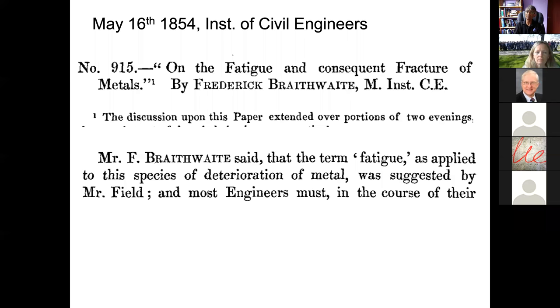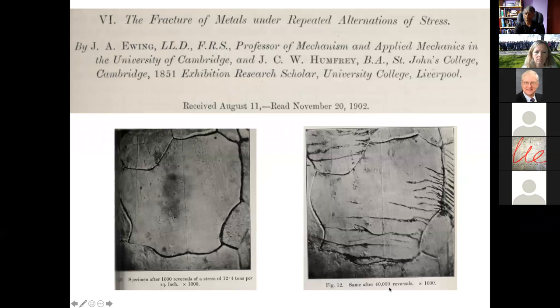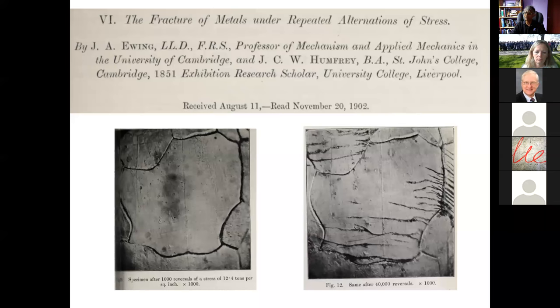The original paper was in 1854, and in 1902 these might be the first metallographic observations to show that even though you are repeatedly loading the material at a stress well below the macroscopic yield stress, there are microscopic phenomena which happen. Before any stress reversals, and then after 40,000 stress reversals you get features developing which are signs of microscopic plasticity happening, presumably at stress concentrations or where compatibility between grains is failing. This was published in 1902 from the University of Cambridge.